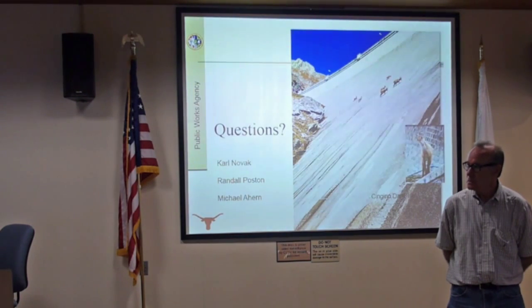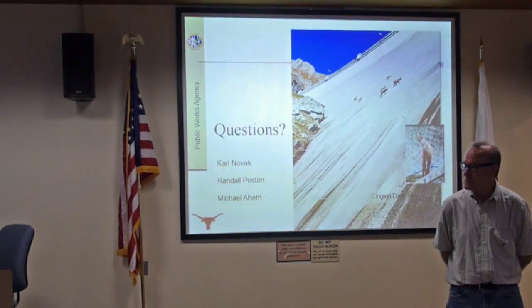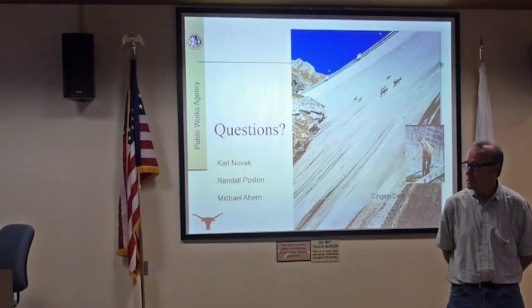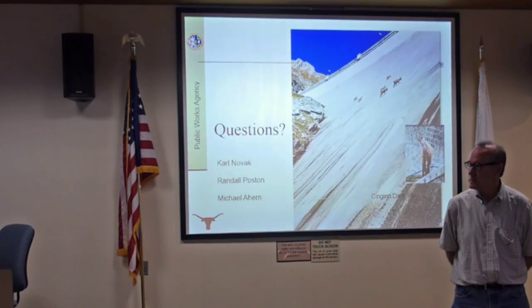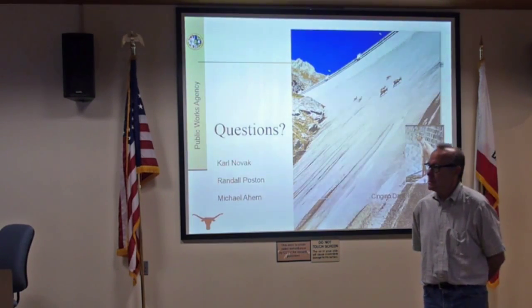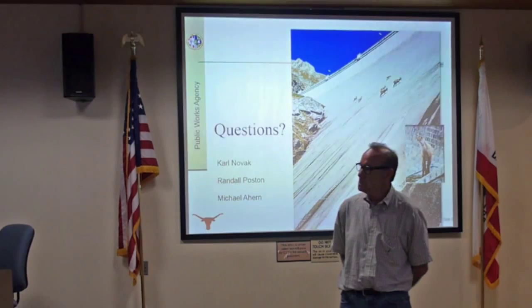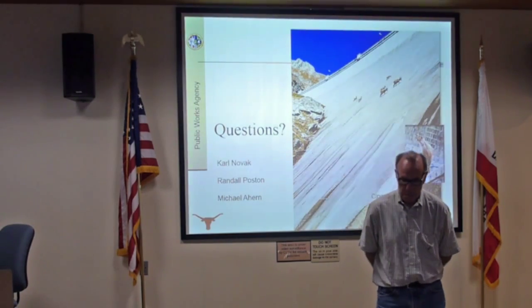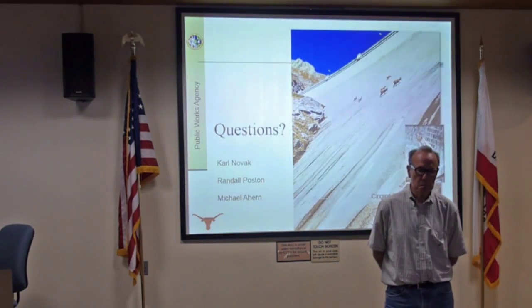And then they tied that to the pier cap through some post tensioning, as well as some bars drilled into the existing pier cap. So they had some buttress type structures at the base, but that didn't elevate the pier, and so they still had the top with the dip. What they ended up doing was cutting the superstructure free, jacking it up, and eventually filling in that 2-foot gap to get rid of the dip. Basically it came on top of the hammerhead and put 2 feet of concrete or something below the supports. Sure.